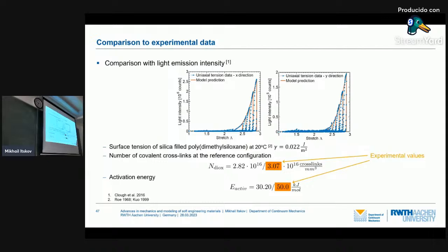Here is another elastomer. These are results from the group of Professor C. Besman from the Netherlands. They did this experiment with dioxetane and shared these results with us. And you see rather good agreement with this experimental data, this light intensity again. Interestingly, the number of dioxetane molecules is also very well predicted in our model.